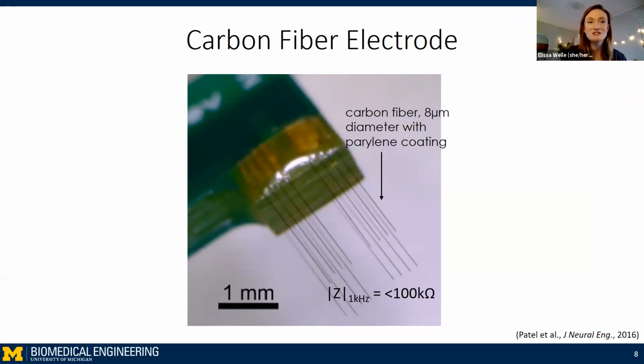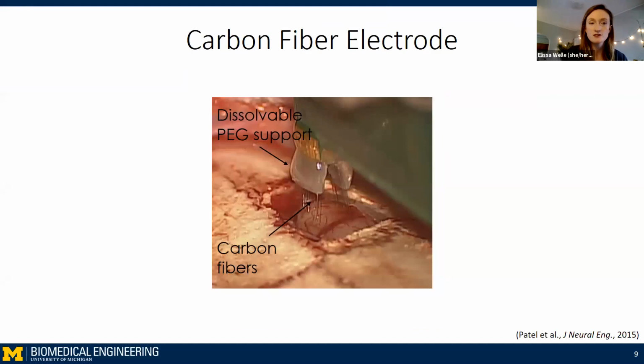And so carbon's a really unique material. It's electrically conductive, it's chemically stable, it has high tensile strength, and also very good fatigue resistance. And I'll talk some more about that later. But one of its best properties is its subcellularly sized diameter. And so, you think that maybe these are too small to insert. They're only 8 microns. But because of its inherent stiffness, carbon fiber is able to insert with very minimal assistance from a dissolvable PEG coating. And so we can insert these tiny fibers into the brain as an array structure.